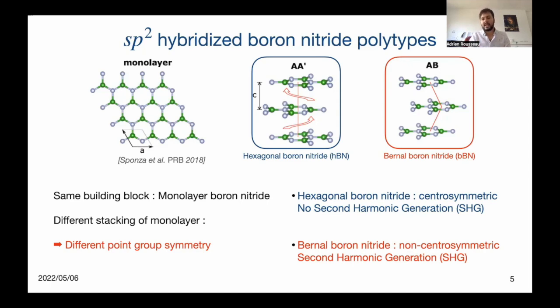As an example, the hexagonal boron nitride is centrosymmetric, and the second harmonic generation in hexagonal boron nitride is forbidden. On the contrary, Bernal boron nitride is non-centrosymmetric, and the second harmonic generation is allowed.